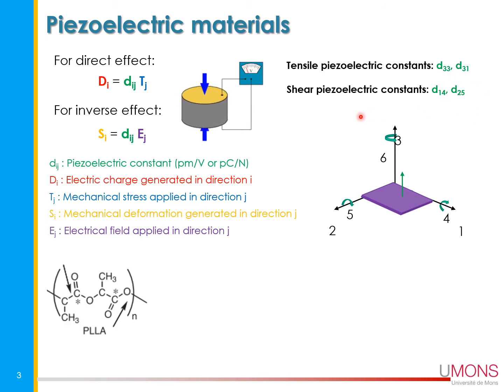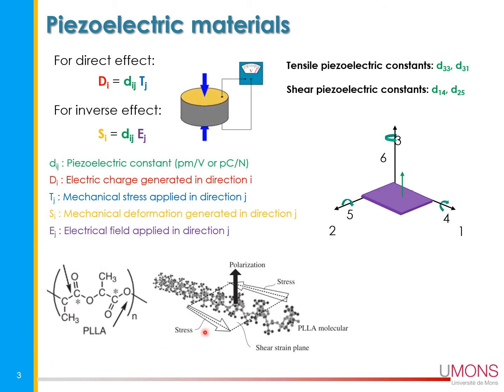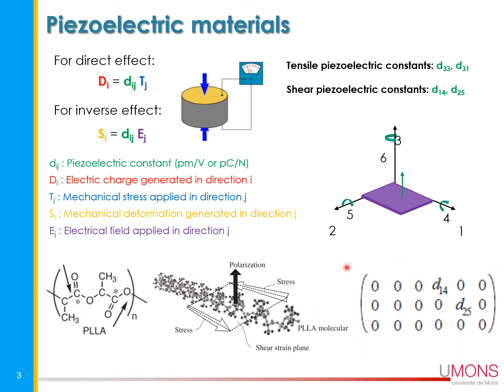Just a reminder for the PLA, we have this chemical structure of PLA here, and as mentioned before, if you want to get the polarization out of this material or this polymer chain, we have to apply a stress or a shear strain to generate the polarization, corresponding actually to this tensor with the D14 and D25 as mentioned before.